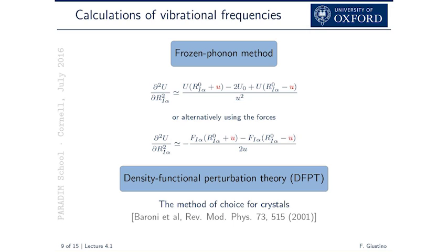We want essentially second derivatives of the total energy with respect to position. That is essentially the first derivative of a first derivative, right? Which is a trivial statement, but we know that the first derivative is minus the force, okay? So that's minus the force on a given atom. Instead of calculating second derivatives, which requires 1, 2, 3 points, if you do the derivative of the force, you only need 2 points. Since the force is something that you've seen yesterday in tutorials, it can be calculated quite easily now.